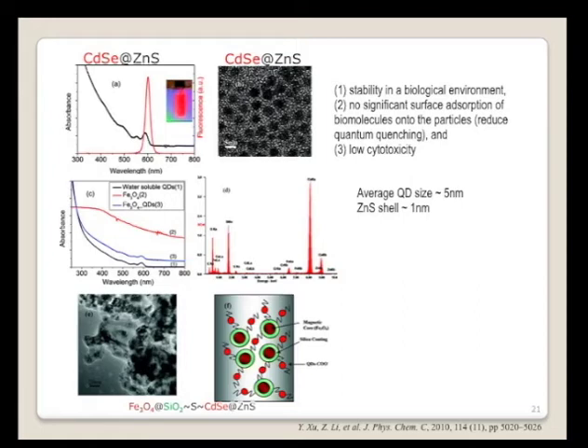See that? Okay, this is a TEM image. You see the black dots here. These are the iron nanoparticles. The small dots around the dark dots, this looks pretty great, are from the cadmium selenide quantum dots. Right. This is the schematic diagram of our composite. So from the image, we can see the average quantum dot is about 5 nanometers. This coating shell is 1 nanometer, very thin.